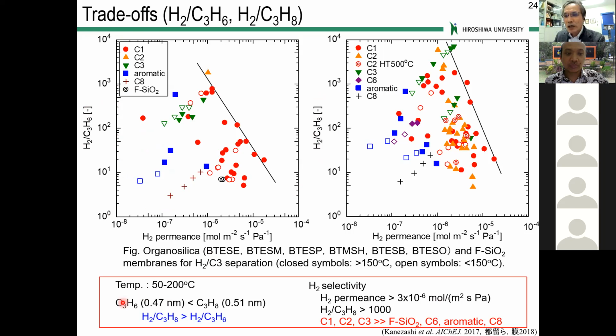You can see propylene is smaller in size than propane. So selectivity is larger for hydrogen over propane. When you look at the hydrogen permeance, it is very large, with a permeance of several 10⁻⁶. When you look at the upper boundary, you can see the C1 linking unit and the C2 linking unit show very high permeance and selectivities.